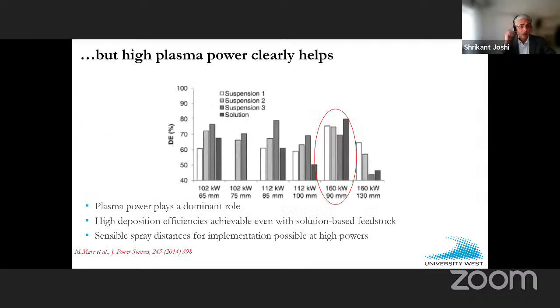But that was then, because soon people realized that use of high power plasmas clearly begins to help when it comes to determining the deposition efficiencies, and you get pretty good numbers here, right? This is an old paper which provided very valuable insights into how plasma power can influence deposition efficiency when you use a solution precursor or a suspension.